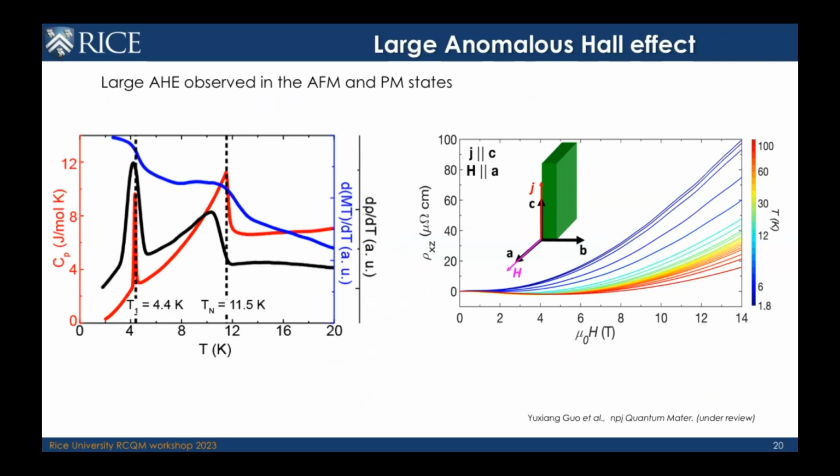First, by showing you briefly that it does order antiferromagnetically. Both our data and others before us have confirmed that, although the magnetic structure is not the easiest to solve because of an incommensurate magnetic structure that's apparent, and because of, I understand, samarium's high absorption for neutrons. So what we know is that the magnetic order is antiferromagnetic, and possibly incommensurate.